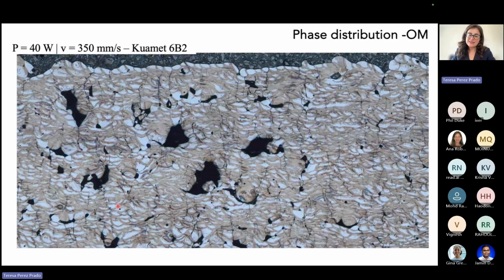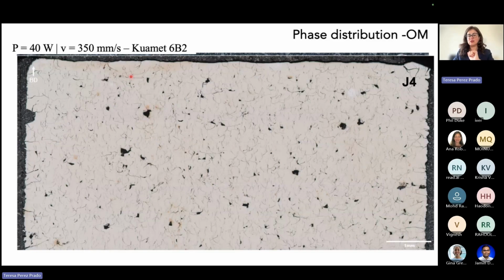So I bring you back this optical micrograph of the Kuamet process sample, the composite. We had these brown regions, crystalline regions. We did the same: we polished one of the cubes made from the new alloys the same way, and we etched the surface, and this is what we get. At least within the resolution of this technique, we don't see any crystalline regions.